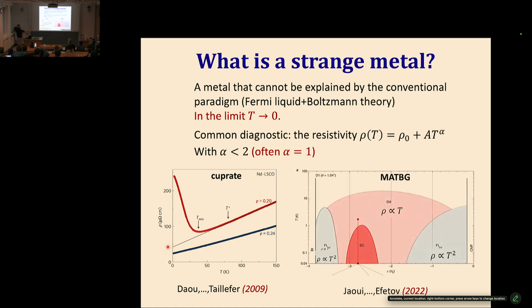And here's another topical example. This is magic angle twisted bilayer graphene, and the experiment finds that over a wide range of electron density in the system, the resistivity actually follows this linear in T law. Sometimes down to strikingly low temperature. This is tens of millikelvin in this system.